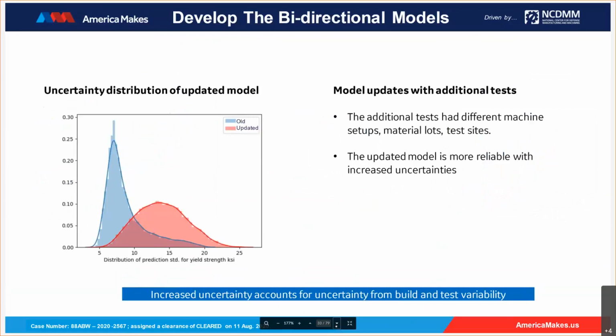After validating the model as reliable on the additional experiments, we now update our model with all the additional testing results, and then we estimated the uncertainty difference. The uncertainty difference is plotted based on a randomly produced 100,000 dataset in the whole design space. Basically, we produced 100,000 sets of process parameters like laser power, etc., and then called BHM to predict at all the grids and plotted their histogram in the shown figure to see the uncertainty difference.